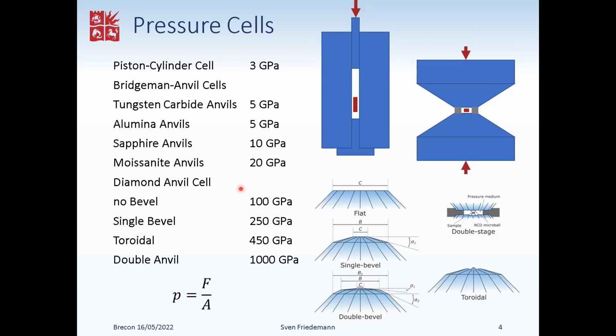Designs have been adapted to make the diamonds reach higher pressures. One can imagine just a flat culet, like indicated here. That maximum pressure with that is about 100 gigapascals. If one wants to go beyond this, one needs a bevel. So that means the slope of the anvil is stepped down before reaching the flat culet. For this, the maximum pressure is about 250 GPa.